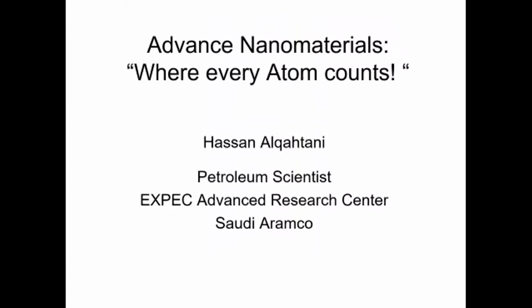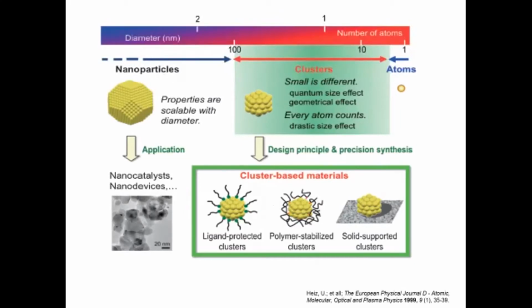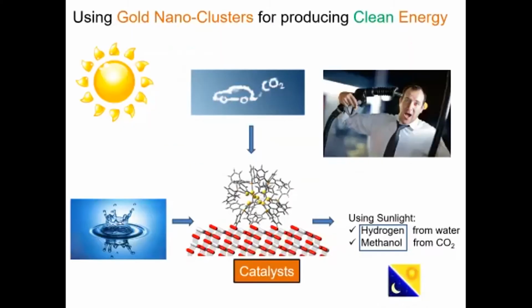When we're talking about nanomaterials, we are not talking about nanoparticles with lots of atoms. We are precisely talking about nanoclusters, which range from 1 nanometer, from 1 atom to 100 atoms. It's a very advanced nanomaterial, and the objective behind these nanoclusters is the production of clean energy. We use them as a catalyst. We enhance the catalytic activity by depositing them on metal oxide, and we convert water by water splitting to hydrogen, and CO2 emissions to methanol.